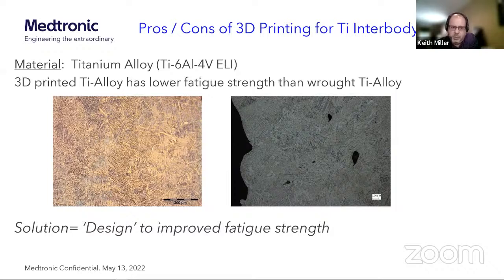That weakness can be due to the grain structure. And also when you 3D print devices, they have a rough surface compared to machined devices. And anytime you have a rough surface, you're introducing a fracture point where fatigue fractures can initiate. In this image to the right, you actually see some porosity. That's from when we were learning the 3D printing process and we didn't have our parameters straight. You don't want porosity in the device. But if companies do not have their laser parameters correct, then you can actually get porosity within the device.